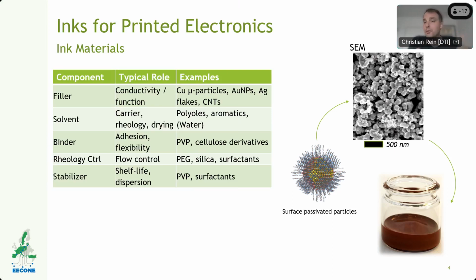The binder provides the adhesion between the material and the substrate, which is very important when you're doing this printing. And then we often also look at the rheology control and stabilizing in order to make sure that the printing process and the lifetime of the ink itself can last as expected. As you can see here in this scanning electron microscope image, you have an agglomeration of particles. Some of them are surface passivated, for example, to provide the right stabilization. All of this is mixed into the ink, as you can see in the picture.